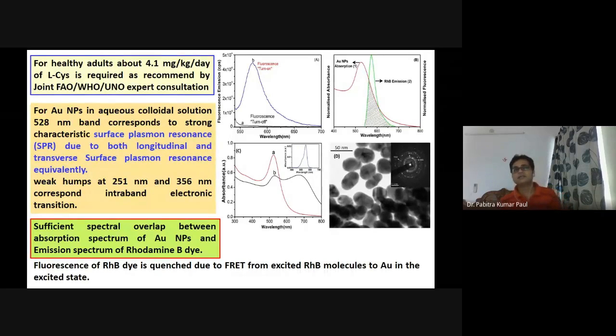We can think of it this way: the separation between the gold nanoparticles and the rhodamine B changes when we add the L-Cysteine, because L-Cysteine is a sulfur-containing amino acid. It can interact very strongly with the gold nanoparticle through the thiol group. So effectively the rhodamine B molecules can be separated, far away from the gold nanoparticles. There is less possibility of interaction between the rhodamine B and the gold nanoparticles, so the intrinsic fluorescence will come out. This is very selective and a very systematic change, so we can measure the fluorescence signal and find out the concentration of the unknown amino acid, L-Cysteine, from the mixture.